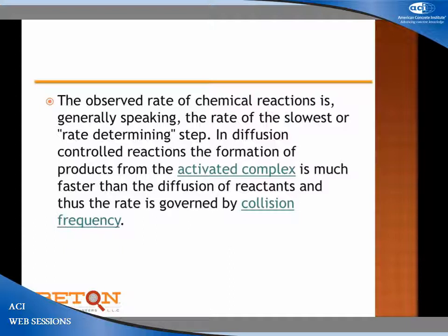And that step is, if you imagine a grain of cement that has begun to react, and those of you who have ever looked under a microscope as a petrographer will know you get a reaction ring around the cement grain, and then the reactant material is hidden. It's covered in that ring. For reactions to occur, water has to diffuse in, or less likely, silicates diffuse out. That diffusion control takes over and the rate of reaction slows down significantly, which is why we need strengths much later in age, and which is why, by the way, if you plot strength versus the logarithm to the base 10 or whatever base you feel like using, you will get a straight line. It's telling you it's in diffusion control.